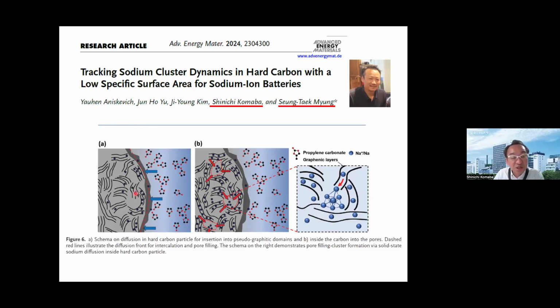So at the initial stage of sodium insertion, sodium goes into the stacked carbon layers. But by applying lower potential, this intercalated sodium gathers and fills the interstitial nanopores. So this process can be believed to mean that sodium can diffuse not only across the SEI, but also, in order to approach the nanopore filling mechanism, sodium can move through the stacked carbon layers. Based on this consideration, sodium diffusivity was evaluated through impedance and also an additional technique. You can see details in this paper.